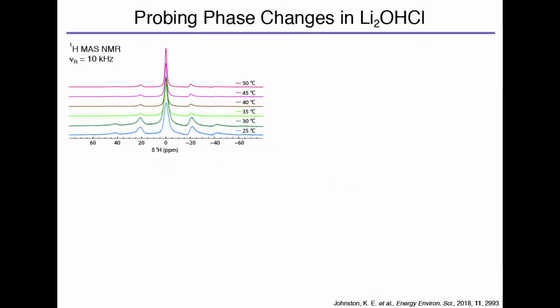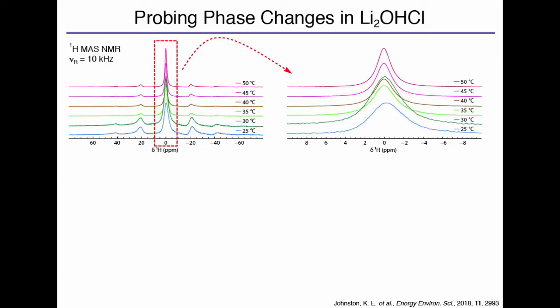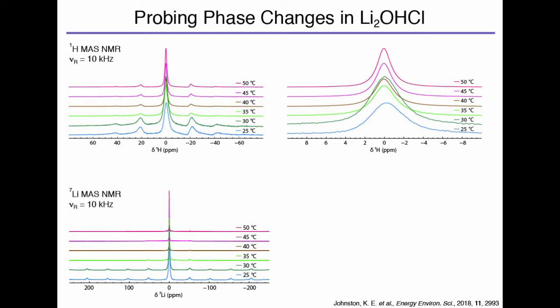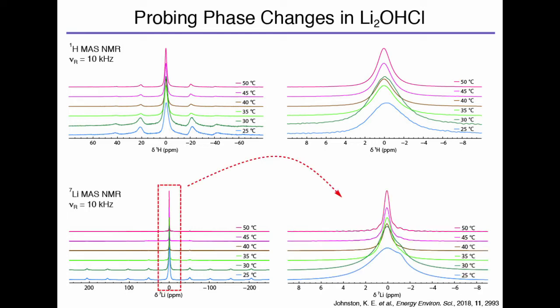We also tried to do this through NMR. And remember, just think about NMR quite simply, just how many peaks do you have and what are they doing, right? That's all I want you to take from this. So in the proton NMR, we can do this as a function of temperature to try and look at what's happening to the proton environment. And if we zoom in on that central peak, because that's the bit we're interested in, you can see that it starts very broad at room temperature, but then it gets narrower as we increase the temperature. And this is what we would expect to happen in these types of systems. We can also do this for lithium-7, and again, we're going to zoom in on that central peak, and you can see we have something that's really broad going to something that's narrow as a function of temperature, so something's changing in there.